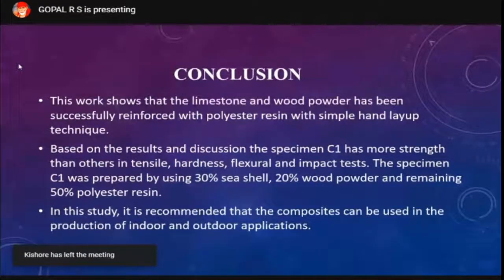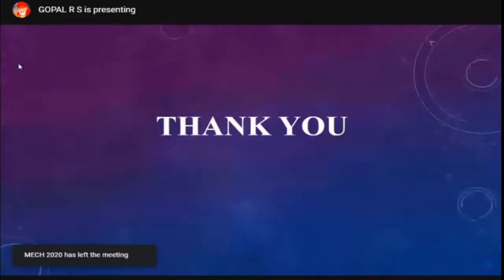This work shows the material has been successfully reinforced with polyester resin using a simple hand layup technique. Based on the results and discussion, specimen C1 has more strength than the others in tensile, hardness, flexural, and impact tests. Specimen C1 was prepared using 30% sea shell, 20% wood powder, and the remaining 50% polyester resin. In this study, it is recommended that the composites can be used for indoor and outdoor applications. Thank you.